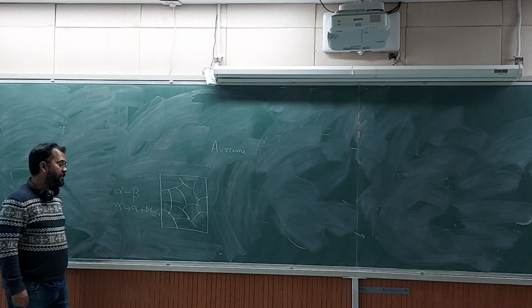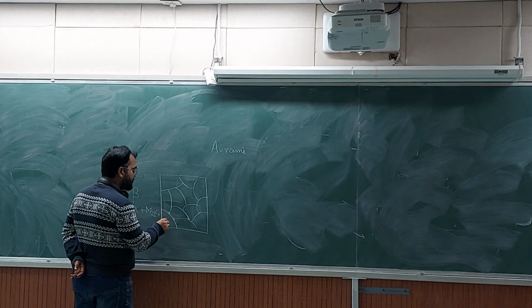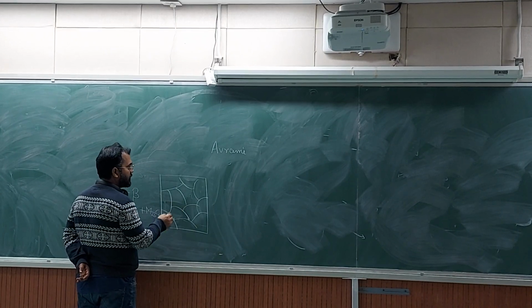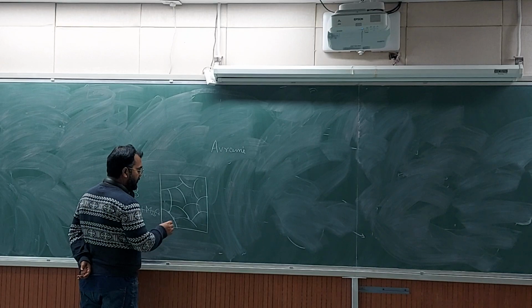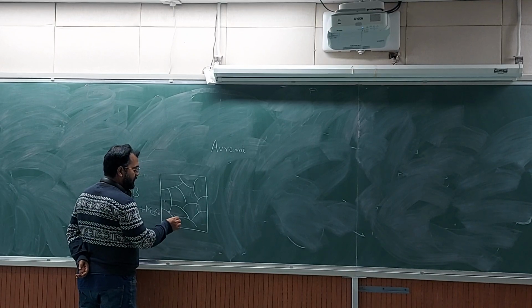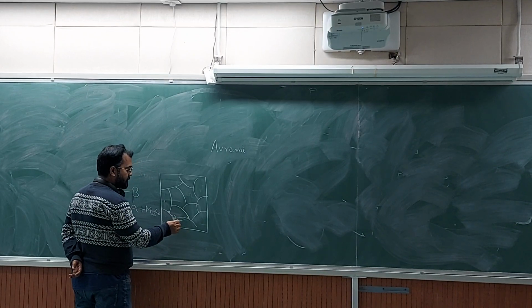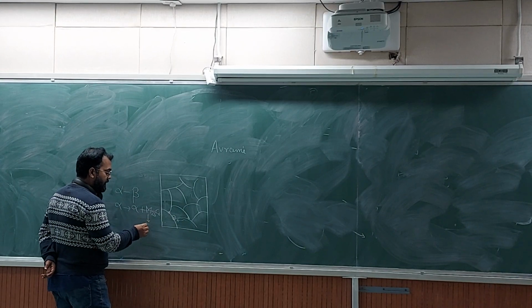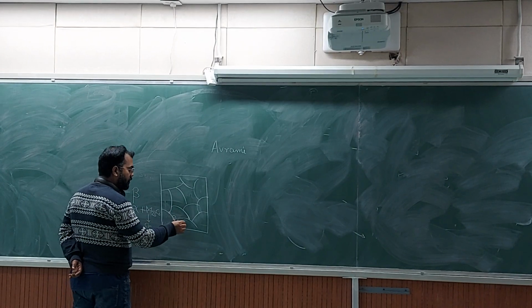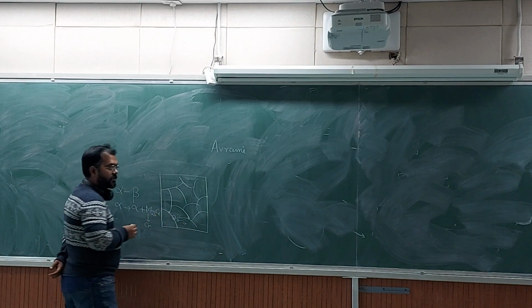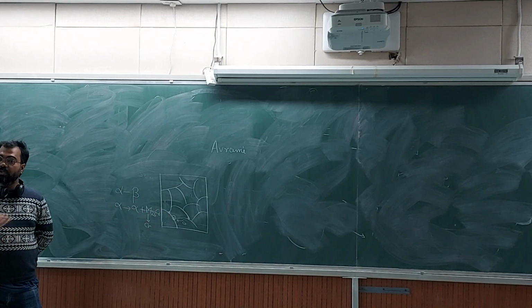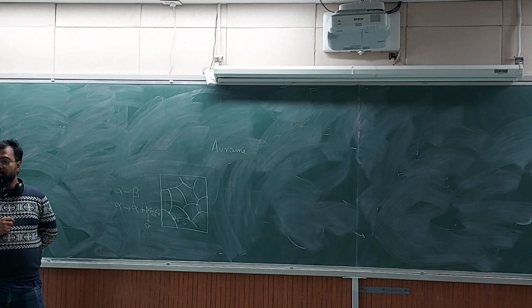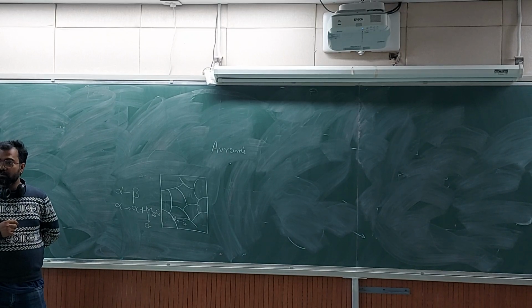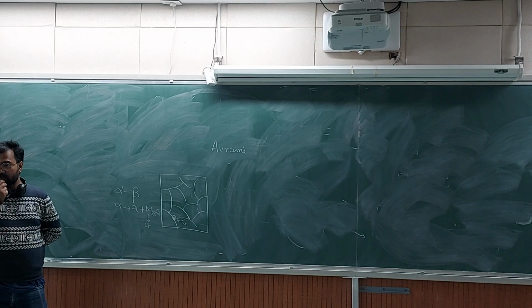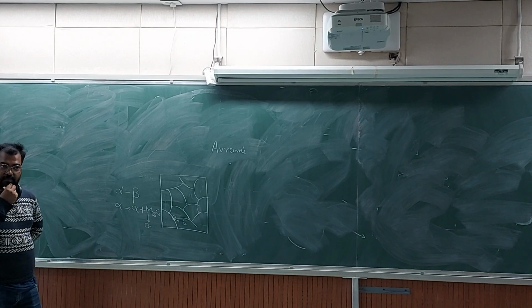So you will have some nucleation inside and some nucleation on the grain boundary, and then they will grow, and they will grow via diffusion, right? So if in this case M is chromium, then chromium will diffuse from the grain or through the grain boundary. So diffusion is fastest on the grain boundary, right? Because they don't need a vacant site next to them. And